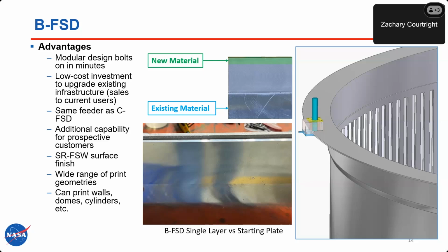So this image on the right kind of shows how beyond a dome, it could be used to actually print the flange as well. So you can imagine where that little blue piece is sticking off the left, that's where the filler material would come in. And then you've got your spindle coming down from the top in blue. And then that containment mechanism basically just contains and drives the material into the prior passes to make that monolithic